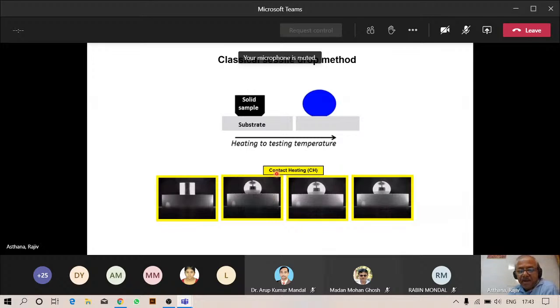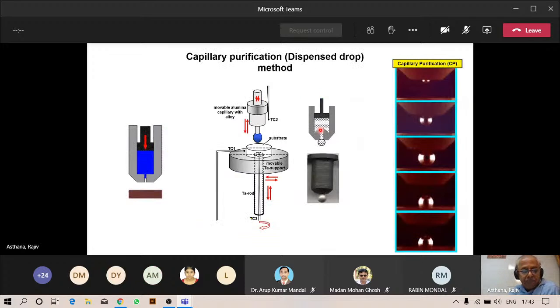The problem is that if you want to investigate the interaction really scientifically between liquid and solid, this approach is not good because during heating in the solid state, there are reactions taking place, not just between the liquid and the solid. So a better method that's used is the so-called capillary purification, where you squeeze out the liquid metal out of a capillary made out of either high purity aluminum oxide or sometimes graphite. So you melt the metal separately, you heat the substrate separately, and when the temperatures are right, you squeeze a droplet and bring it in contact with the substrate. When that happens, you can actually time the spreading of the droplet. You can control the time for interaction between the liquid and the solid.